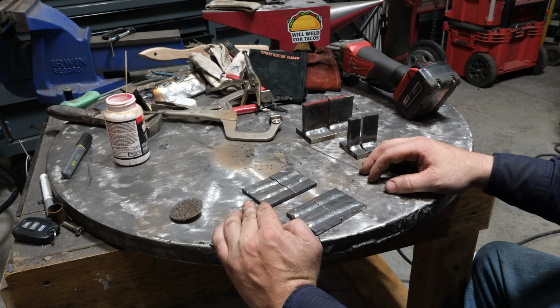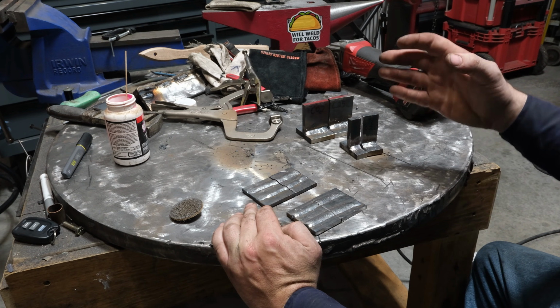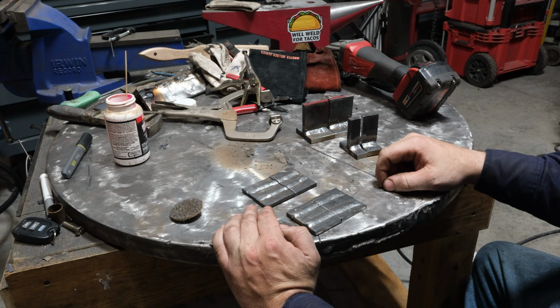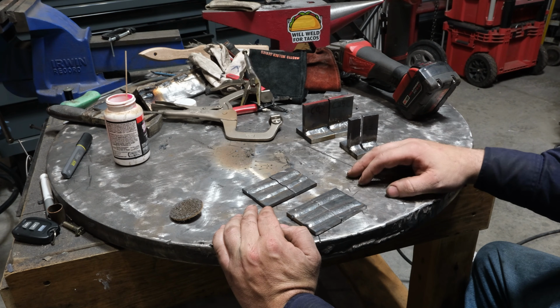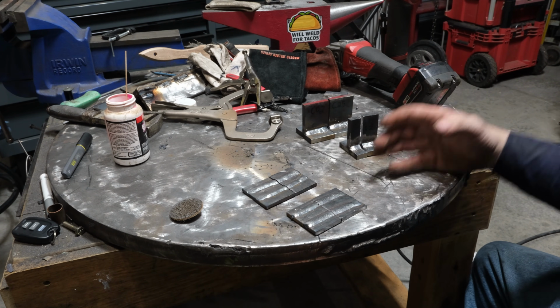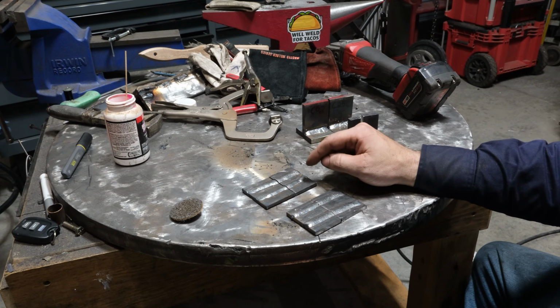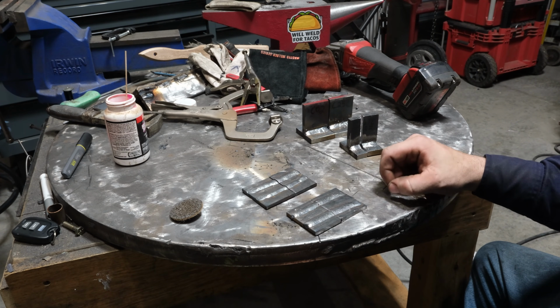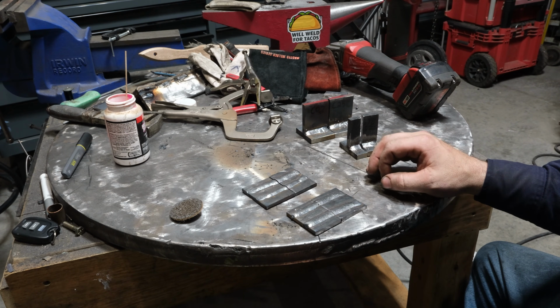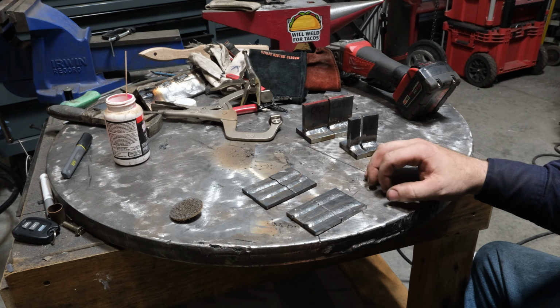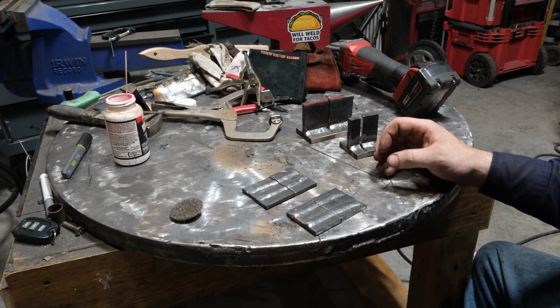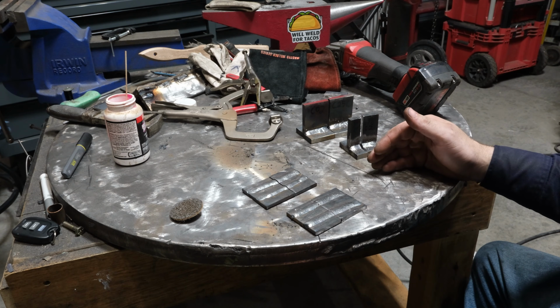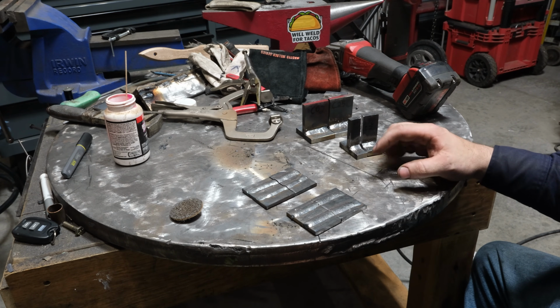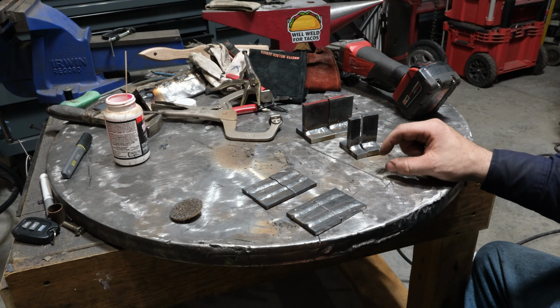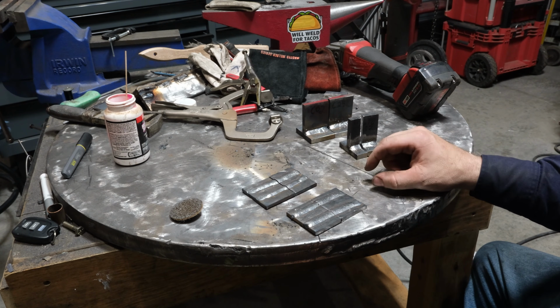Well, I welded up a bunch of test specimens and cut and etched them and looked at the results, and pretty interesting. So right off the bat, a couple things. One, the C25 welds have a little bit of wormhole porosity in the surface. It appears to only be at the surface, and that was a direct result of running a bit too high a voltage.